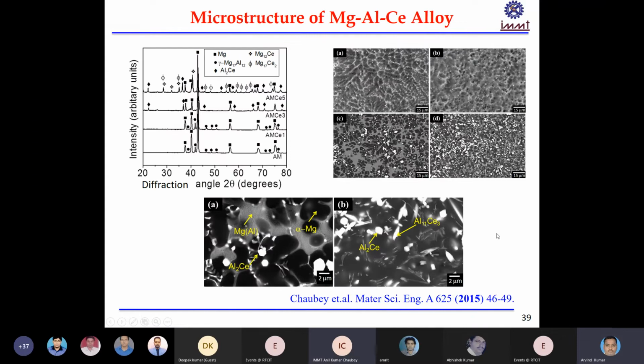So here you can see the microstructure and the X-ray diagram. In the XRD, you can see how the different phases are forming. The magnesium 17 aluminum 12 gamma phase, which is there in pure magnesium aluminum alloys, is reduced at 1%, but at 3% it is completely gone, and at 5% you can see another intermetallic. At 3% there was an Al2Ce phase, and at 5% Al2Ce and a magnesium 17 cerium 2 phase form. So if you go to a higher cerium percentage, another phase forms, this magnesium 12Ce, magnesium 17 Ce2.